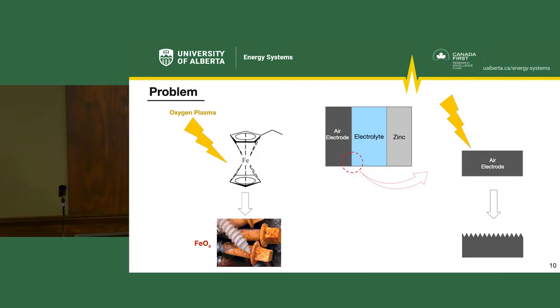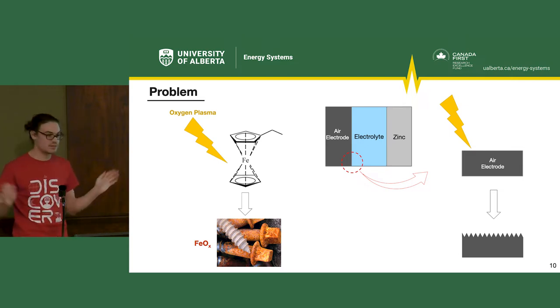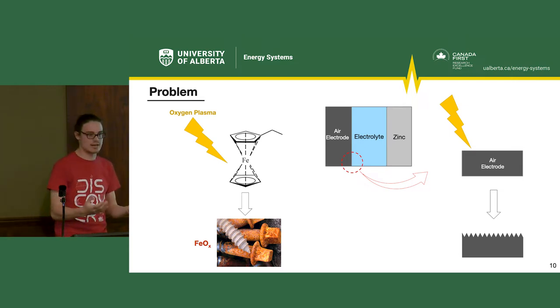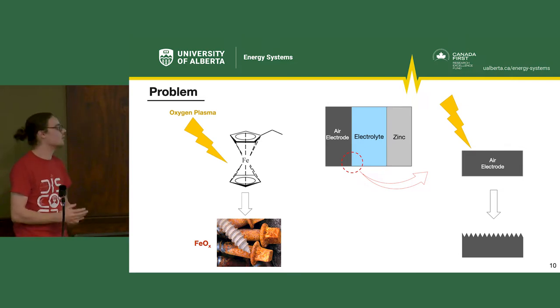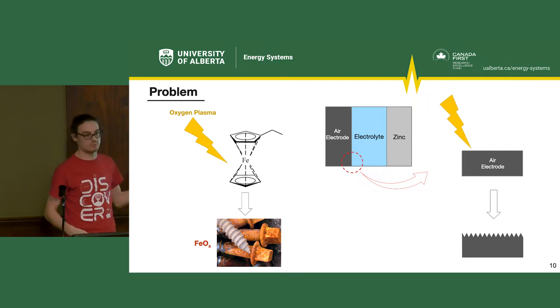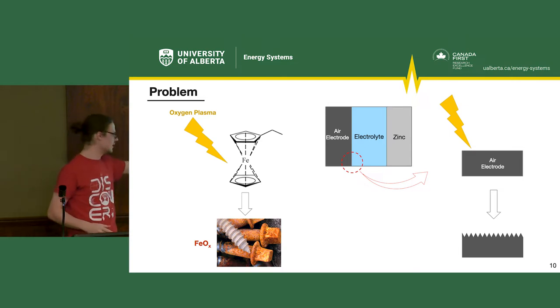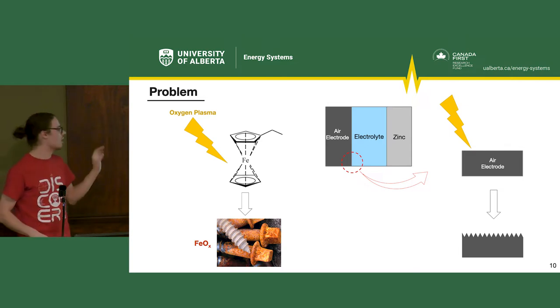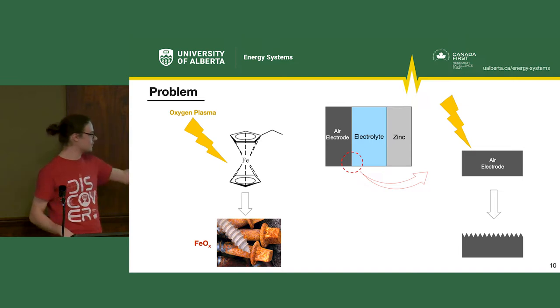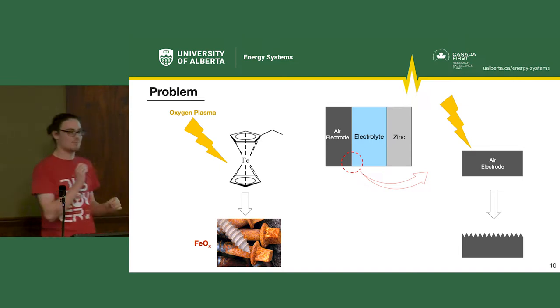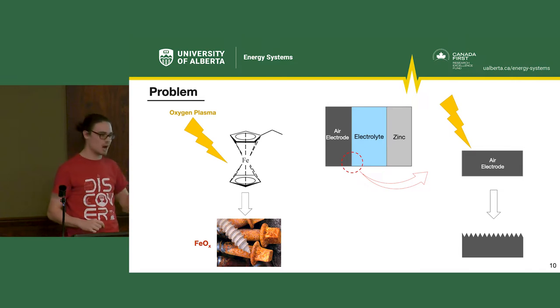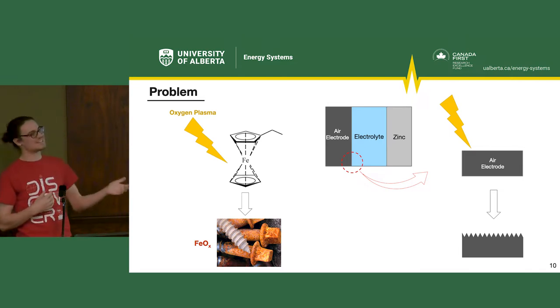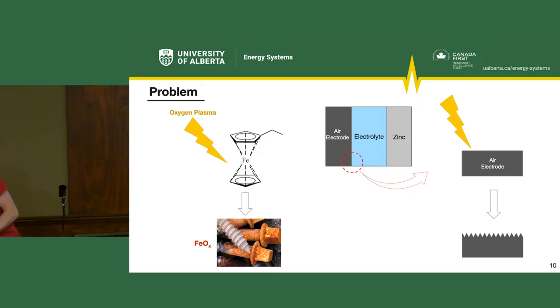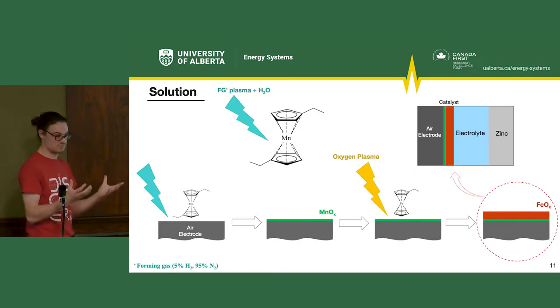Now, when I was doing my research, though, I came upon a problem. So this is the molecule that I use, the gas-based molecule, called ethylferrocene. It's cheap, it's abundant, it's great. To make iron oxide, I had to break those iron-carbon bonds. So I use something called oxygen plasma. Now, it's great at destroying the carbon bonds and giving me iron oxide, giving me that rust. However, when I throw it on my battery, looking at just the air electrode, that same oxygen plasma is great at destroying my carbon-based air electrode. So that's not a really good thing. That's some problem there. So a solution was to have a buffer layer, a protective layer.